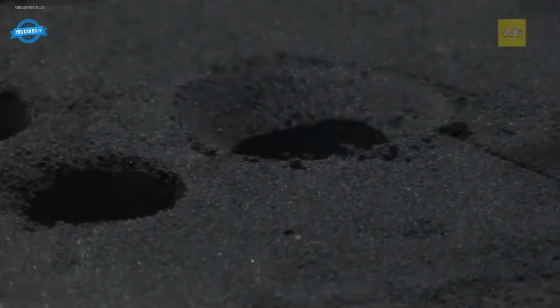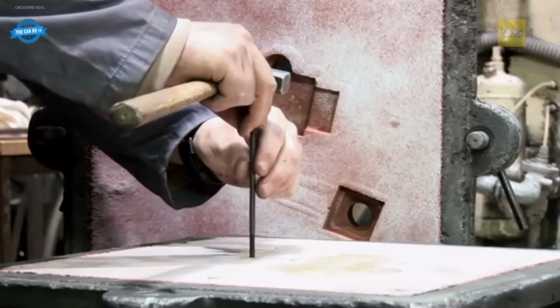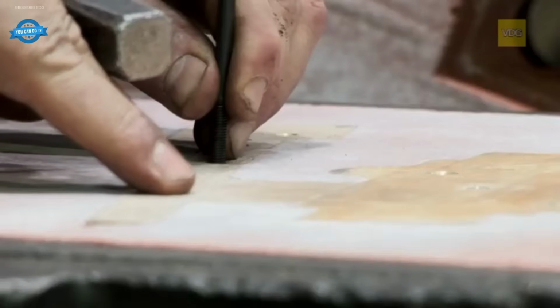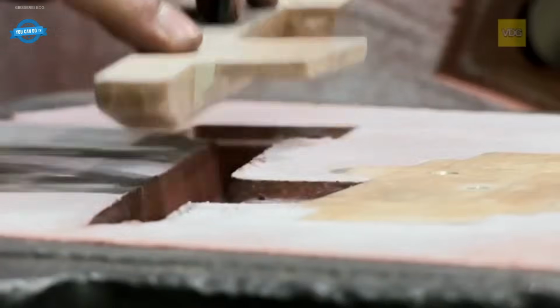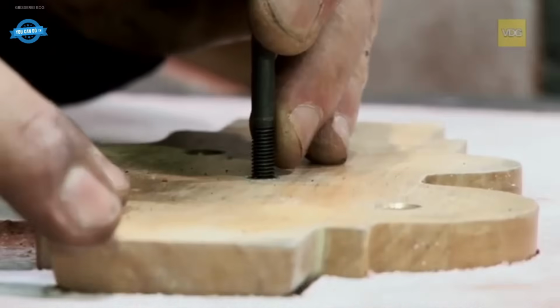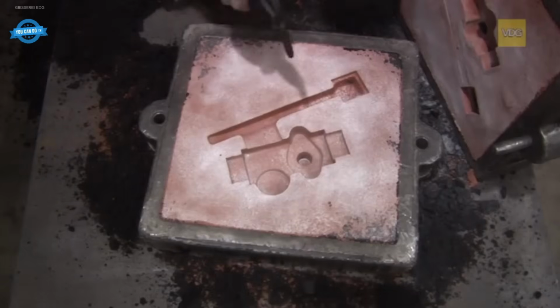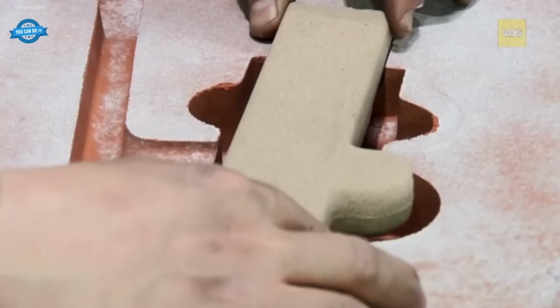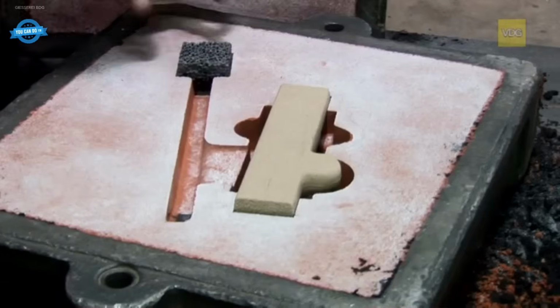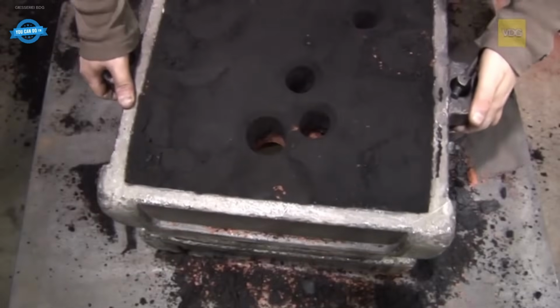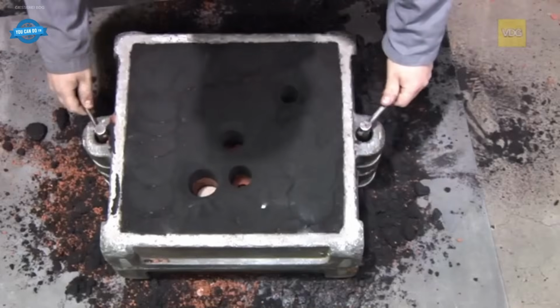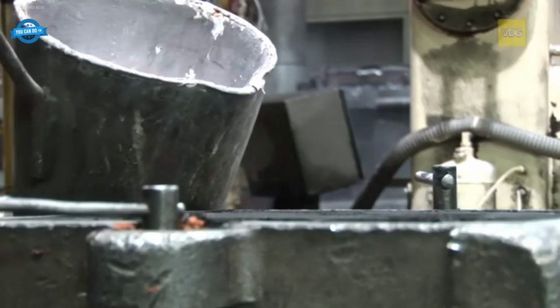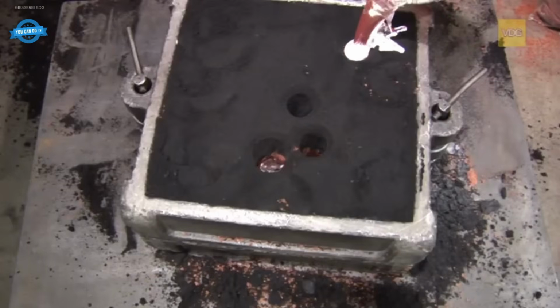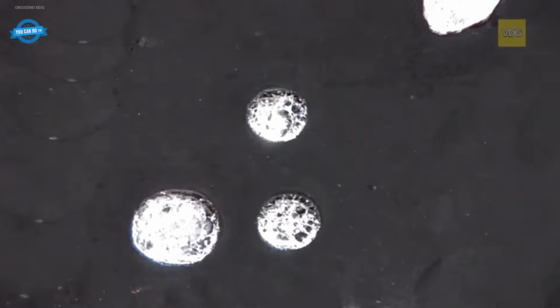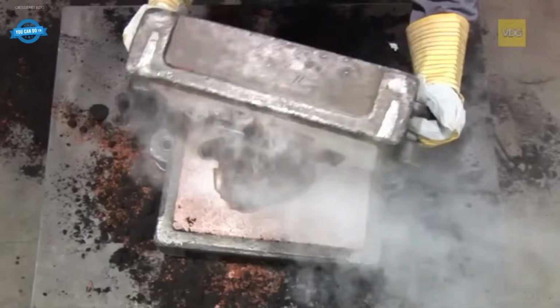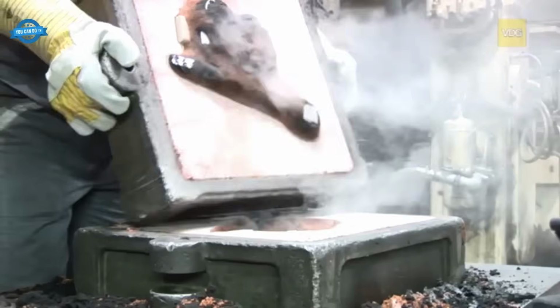Cores define internal cavities or complex undercuts in the casting. These are manufactured in dedicated core-making departments using cold box, hot box, or furan resin systems. The core boxes are precision machined and dimensionally controlled. Once filled, the binder curing process is initiated either through gas, amine catalysts, heat, or air hardening. After ejection, the cores are coated with refractory ceramic slurries to increase surface quality and resist erosion from molten metal.